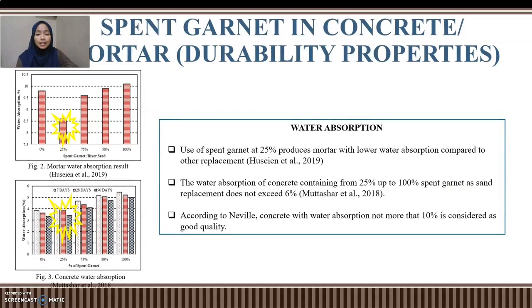The next, I will discuss about the durability properties of spent garnet in concrete or mortar. Based on 2 figures, we can conclude use of spent garnet 25% produces a mortar with lower water absorption compared to other replacement. But we can see from this figure reported by Muttashar et al. 2018, for 25% replacement is higher compared to the control specimen, but the water absorption of concrete containing from 25% up to 100% spent garnet sand replacement does not exceed 6%.